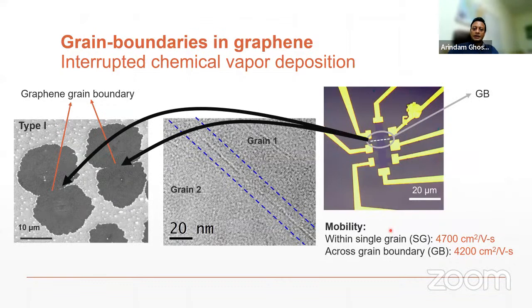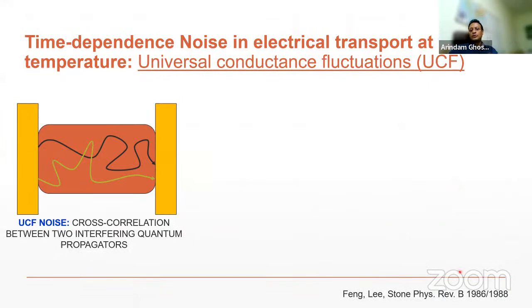But before I go into a couple of experimental slides, let me tell you the physical principle why we believe noise can be a very good probe for magnetic interaction. So that comes from the concept of what you call universal conductance fluctuations. Now, if I take a solid like this and I pass current from one end to the other, the electrons essentially go in random paths, diffusion.